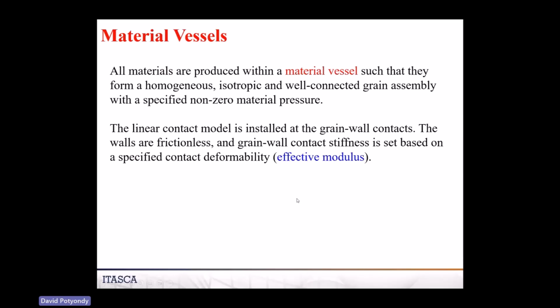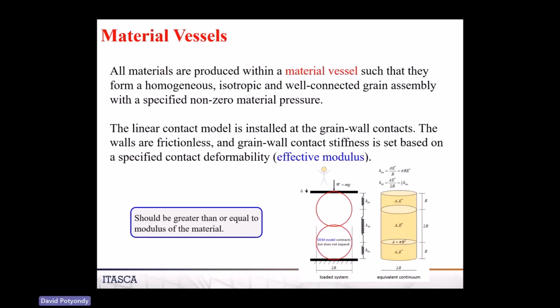What about the vessel walls? What we're going to do in this package is we're always just going to use a linear contact model there. And those walls are going to be frictionless. And if they're frictionless, then the friction coefficient doesn't matter, and the shear stiffness doesn't matter. They're not relevant if they're frictionless. So the only parameter we need at that interface, the ball-facet type of contact, is the Kn, the normal stiffness. But instead of giving a normal stiffness, we're going to give an effective modulus, that E star. So we're going to specify E star for that interface, the effective modulus.